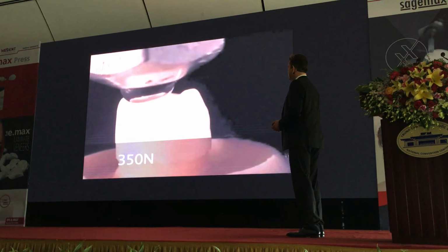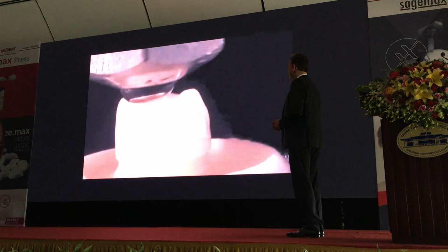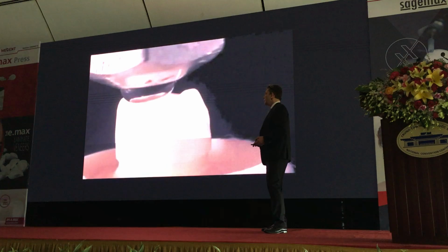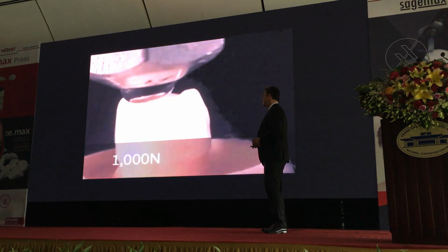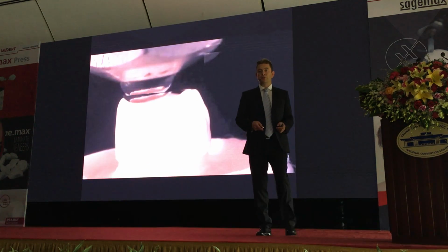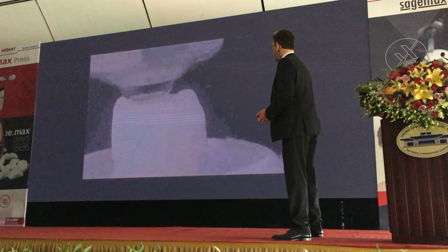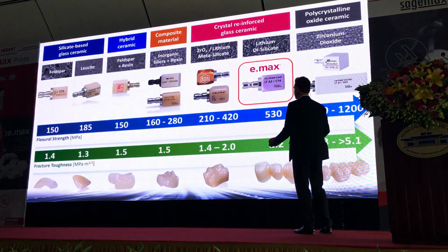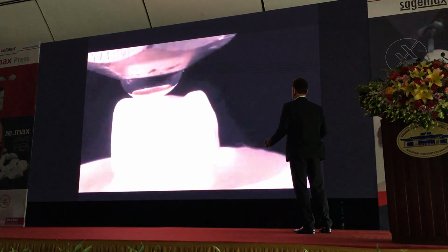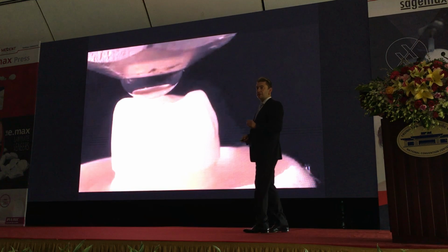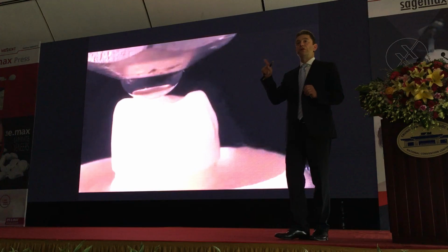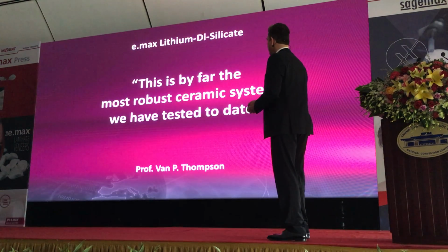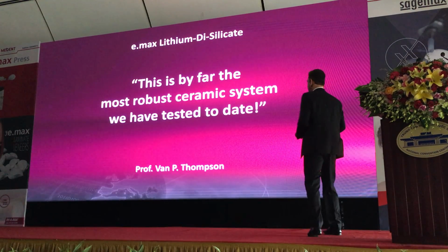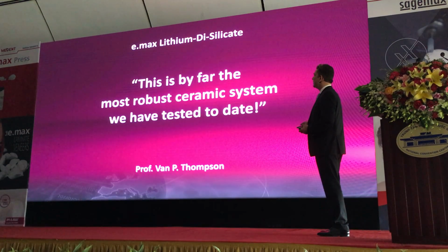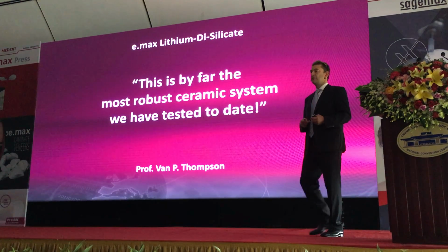And you can see here, in this test, they are hammering with this metal on the crown with increasing loads. So this is 700 newtons, and they go to more than 1,000 newtons. And they do this for millions of cycles. So it's a very, very tough test. And in this test it has been shown that Emax was more resistant compared to layered zirconia. Yeah? That's why we should do monolithic restorations. And that's why the principal investigator, Professor Van Thompson, said that Emax lithium disilicate is by far the most robust ceramic system we have tested to date.